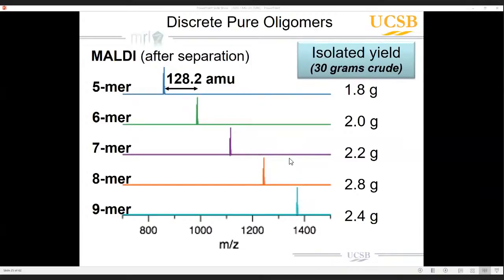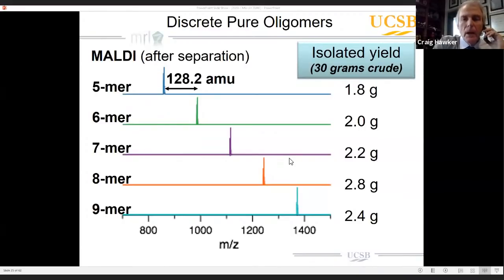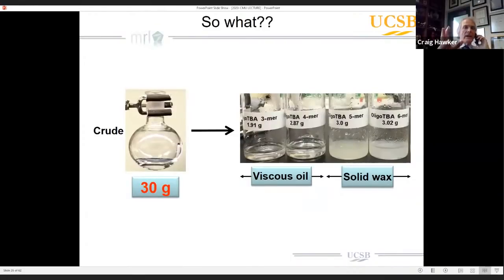But in essence, what I was saying is that we can now prepare and isolate these oligomers in synthetically useful amounts. So you can see here, we can now make grams of these materials very easily. And one of the other nice features about this process is that we can actually start to ask questions about, so what can we do with these materials? So I'm just showing you here the crude polymer that we start with. We can then separate that into the trimers, tetramers, which are viscous oils.